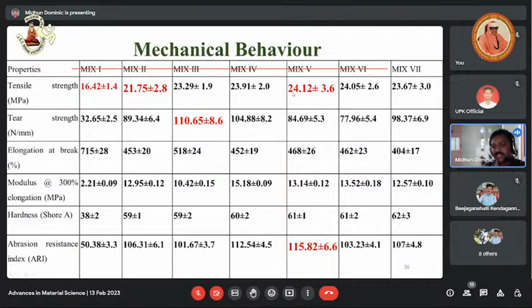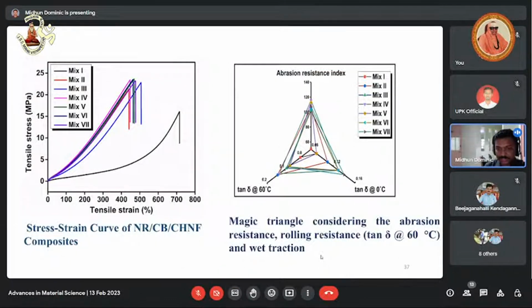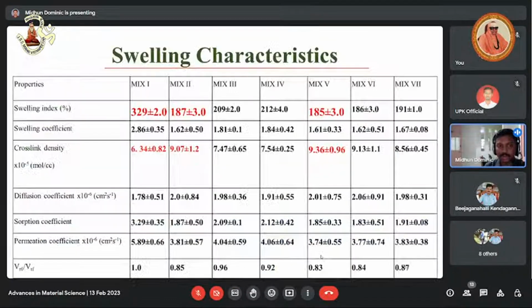Wow, we have succeeded. In the previous examples, tensile strength was decreased. Here, tensile strength is increased from 21 to 24. Tear strength improved from 89 to 110, and abrasion resistance index also improved from 106 to 115. So we could obtain excellent mechanical properties by the synchronized use of carbon black and chitin nanofiber. And this paper is accepted in Carbohydrate Polymers.